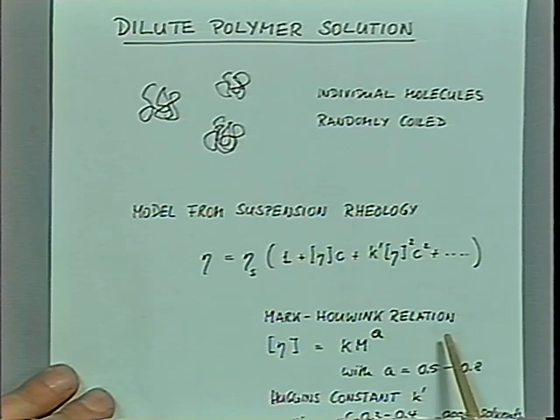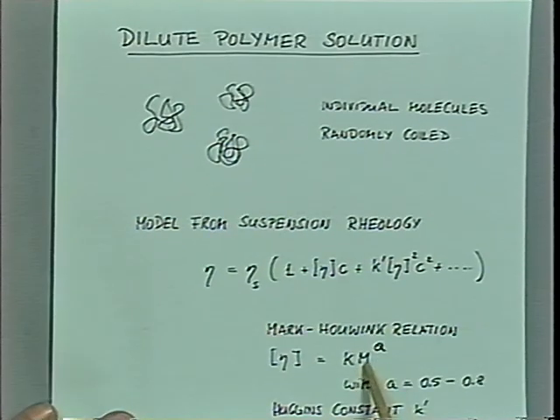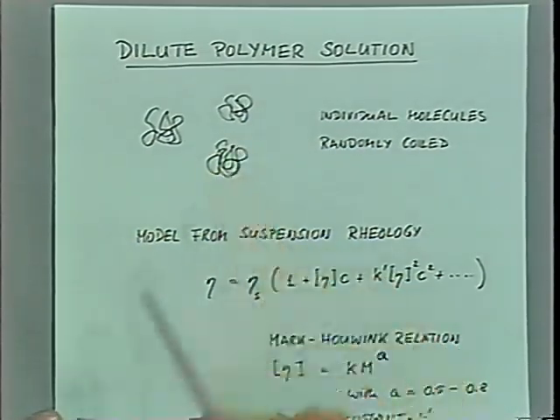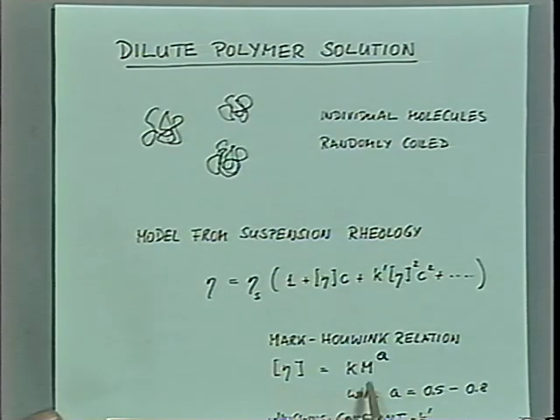Now, the intrinsic viscosity depends on the molecular weight, because the molecular weight determines the size of those molecules, and the relation is given in the Mark-Houwink relation. Note that this exponent is very small. It's 0.5 to 0.8 in that magnitude, so the intrinsic viscosity doesn't change too much with molecular weight. While for polymer melts, the zero shear viscosity would go with a 3.4 power. It would be much more sensitive to molecular weight changes.